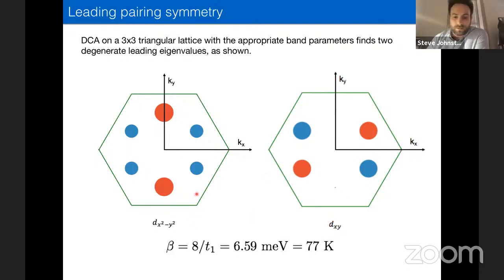So this is our first indication that for the band parameters that we think are relevant for the tin monolayer system, unbiased calculations of the Hubbard model tell us that d+id is really the leading pairing instability. And so that's the one we expect to have happen in the unconventional channel.